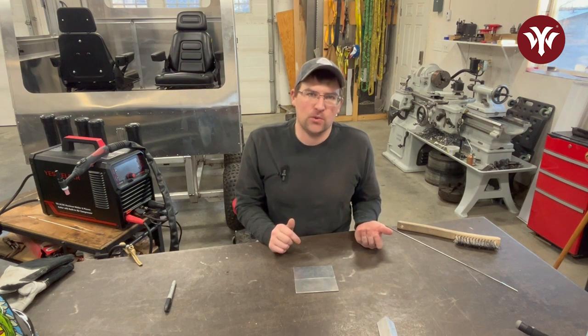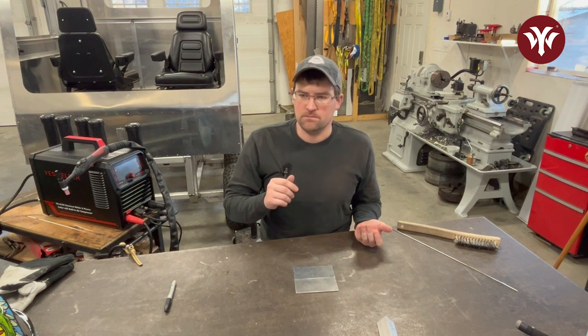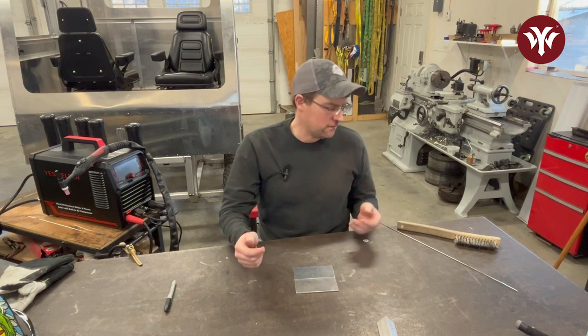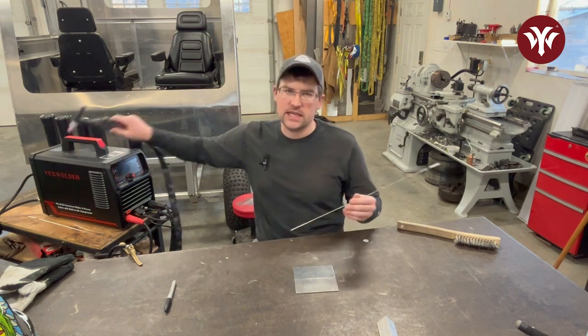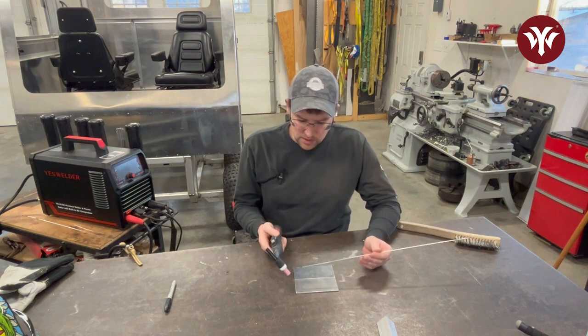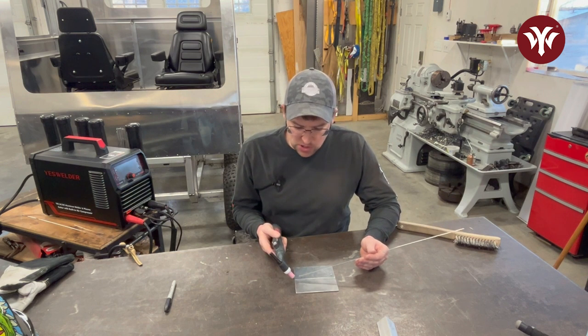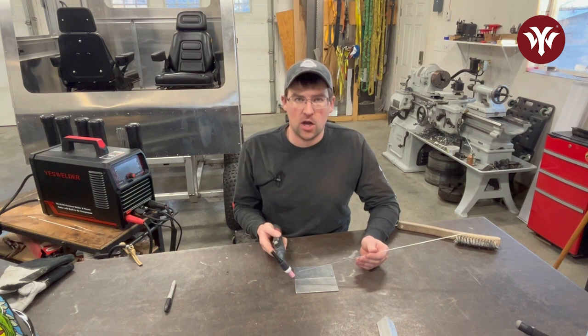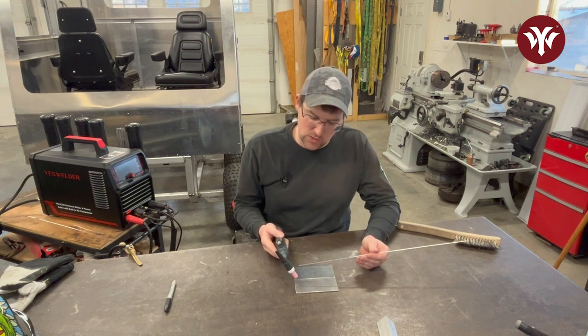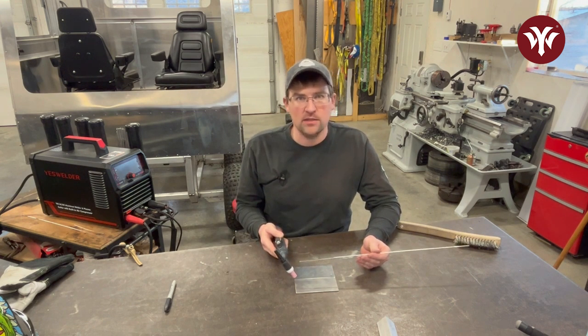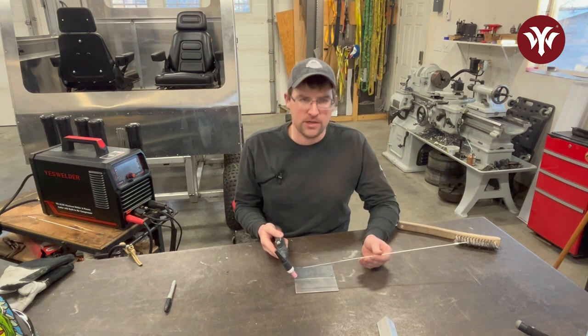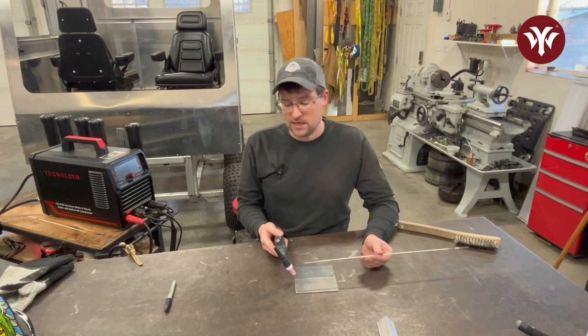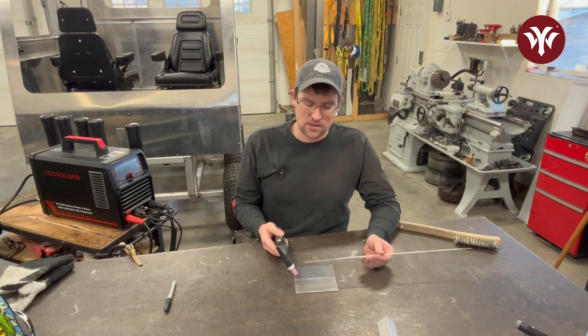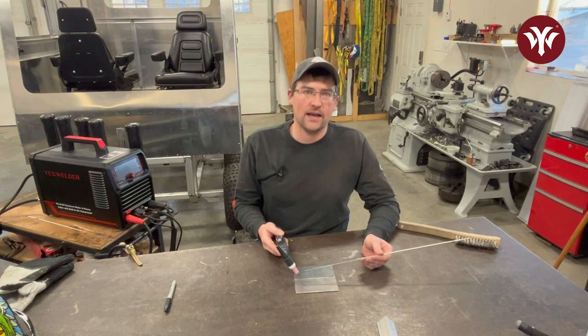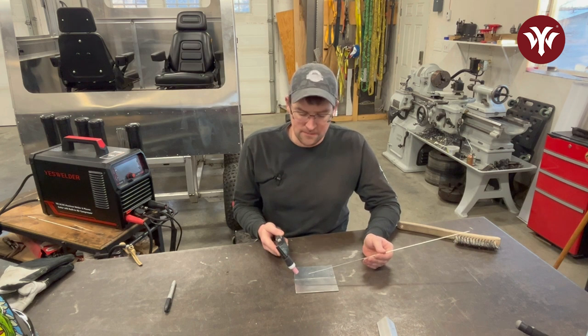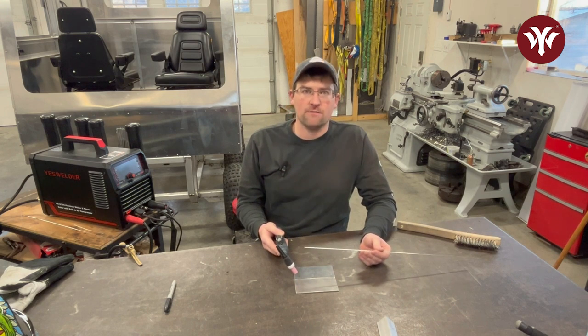Pulse settings are really simple. The only thing to it is the pulses per minute that you're gonna have. And when you're running a pulse with a TIG, it's gonna pulse on, and when it's pulsed on, you dab your filler rod when it's real hot, and then the pulse is gonna back off, and that's when you move the torch. And then the pulse comes on, brings that puddle back to life, you'll dab in your filler rod, and then the pulse comes off, and it's just a process. Really, the pulse sets the rhythm for the weld, because you're only gonna add filler rod when the pulse is on, and you move when it backs off to the low current.